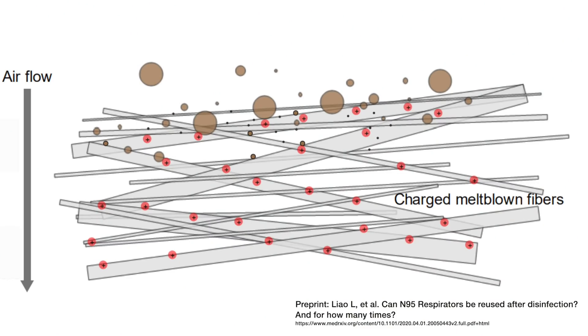Not so. These fibers get charged into quasi-permanent dipoles called electrets, so they get an electrostatic charge. Basically, once this layer is charged, it traps harmful particles. These fibers are electrostatically charged as they are created. This charge allows the mask to filter much better without adding any density, without making it more difficult to breathe through. If this charge is weakened or lost, the mask efficiency plummets.